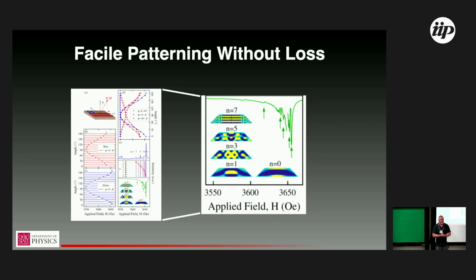This is a numerical calculation using mumax. The green arrows represent magnon modes that are exactly reflected in this blue experimental data, and match the simulation quite well, using no adjustable parameters in the simulation, just the parameters extracted from the angle-dependent FMR and the anisotropy. And the nice thing about MuMax is then we can use that to develop maps. So this is a model of a disk where we've approximated the lens-shaped cross-section just with a linear profile. And the color scale is the phase of the magnetization.